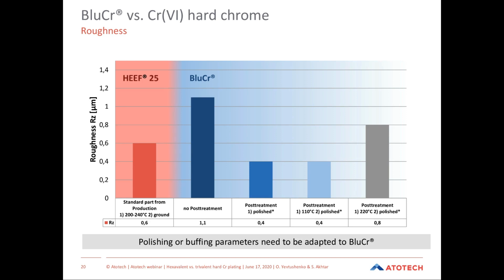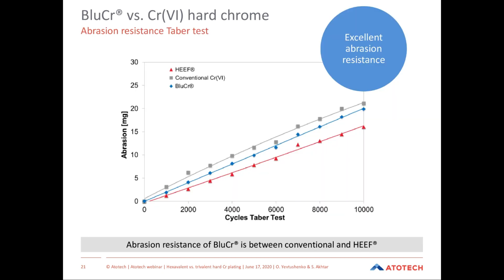However, at this point, it must be said that in doing that, some adjustment of grinding parameters needs to be done. As the blue chromium layer is softer compared to hexavalent, you need to apply also softer grinding conditions to achieve at the end the same or even better quality.